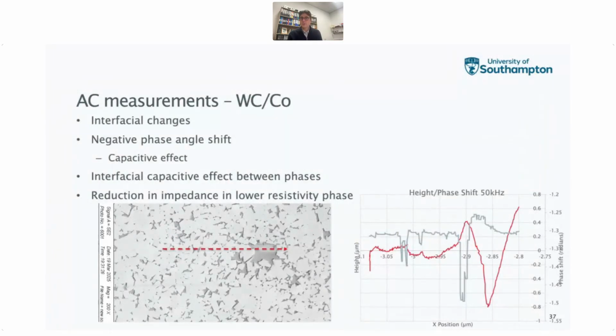So this is early work for us at the moment. We're still trying to unpack this a little bit, but we think that perhaps the impedance might be able to delineate between interfaces, between phases, and possibly also the absolute values. But we think that might be a way to pursue looking at trying to correlate the surface features of different phases with the topography, with the electrical contact resistance measurements using an alternating current.